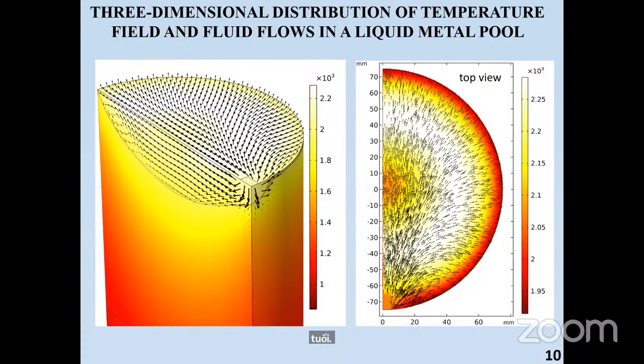Slide 10 shows the calculated three-dimensional distribution of the temperature field and the direction of the velocity vectors of the metal flow in the crystallizer, with reduction of the ingot pulling speed to the bottom. The stream of liquid metal spreads from the place of its pouring to the walls of the crystallizer, forming a small vortex. From the top view, a diametrical distribution of metal flow is observed, which is caused by the action of the flow from the liquid metal pouring into the crystallizer and the thermal power from the electron beam.